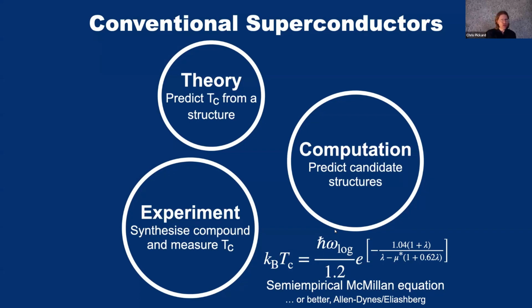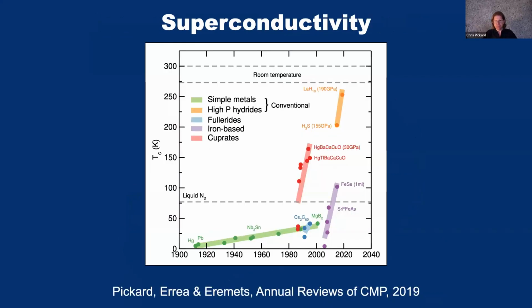We're in a very nice situation where not only can we predict structures, so this first principles structure prediction allows us to bring up candidate structures, even if the structure type has never been seen before in any experiment. So we can search combinatorially through all the possible structures that there might be. At the same time, using codes such as Quantum ESPRESSO and density functional perturbation theory, for a given structure we can compute the superconducting transition temperature. And then, of course, experiment can be done to make measurements of these structures. So this loop between these three different approaches has given us a computational way to do discovery of new superconductors. And this has been fruitful.